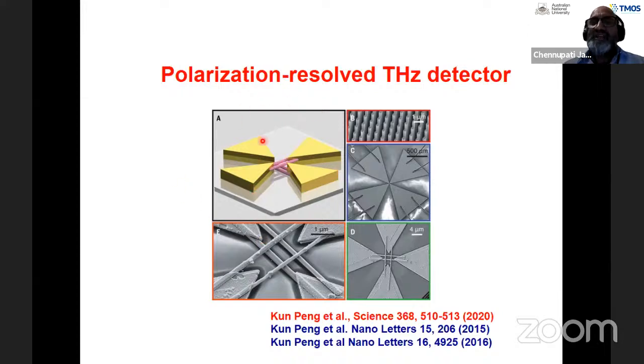She spent about 3 years working with my colleagues at Strathclyde University to develop these things. And you can see the close-up of these structures, the nanowires and the antennas. The challenge has been that the nanowires on the top should not be in contact with the bottom nanowires. And that's where she had to spend a lot of time optimizing the fabrication conditions, for example.